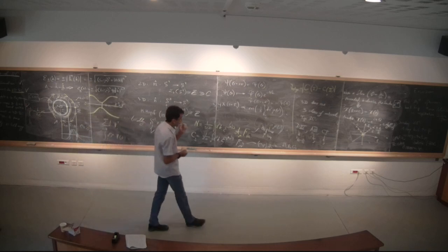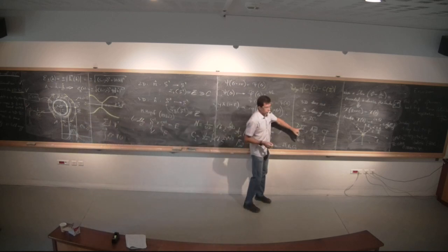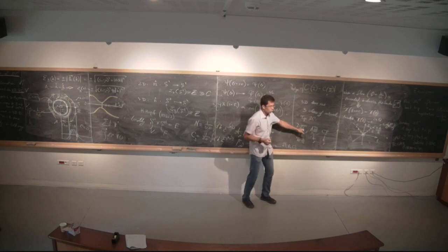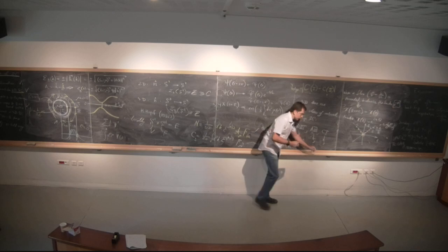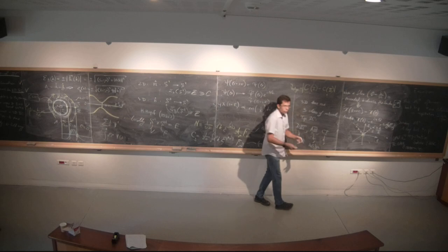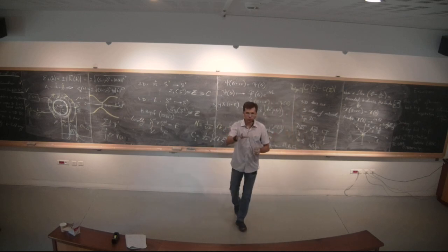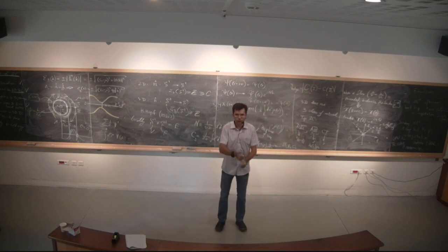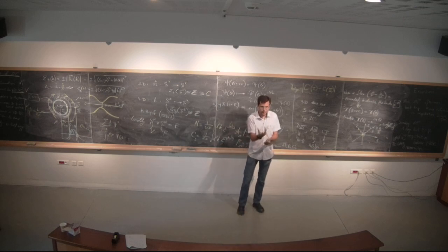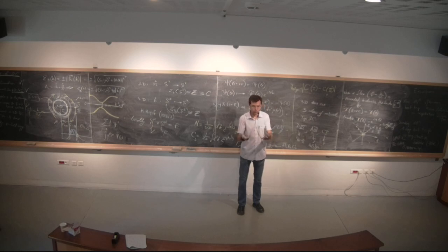What would be the guidance? Well, if you think of class D3, helium-3B has a very strong spin-orbit coupling, so spin is not a good quantum number. If you ask what's the difference between this one and this one, the A phase has a well-defined U1 spin symmetry. So what does U1 mean? It means X and Y may not be well-defined, but there should be a good easy axis. So if you have an idea of some element that has an easy axis, like an easy axis magnet, if you could make it superconducting, that's a clue.